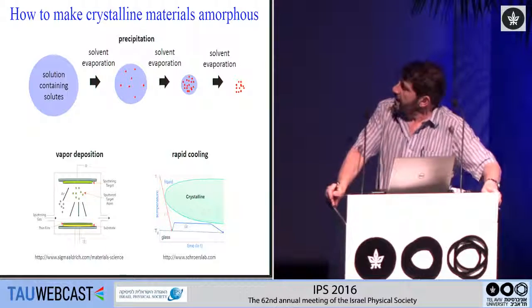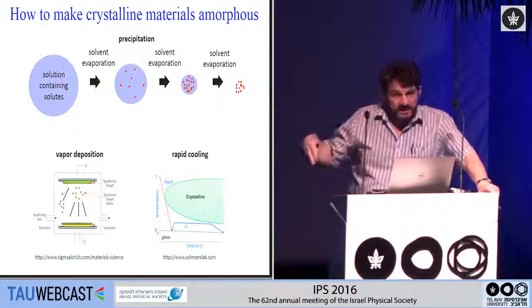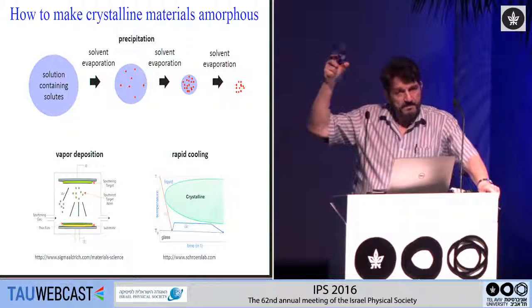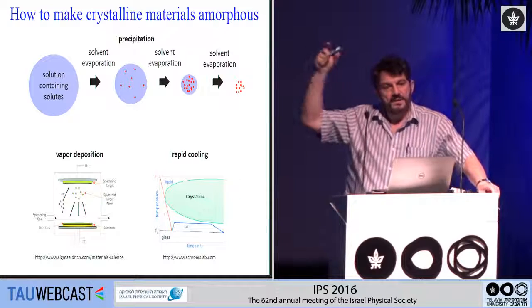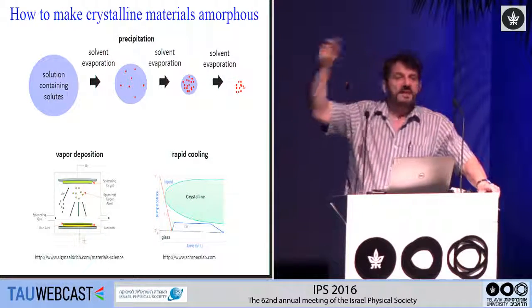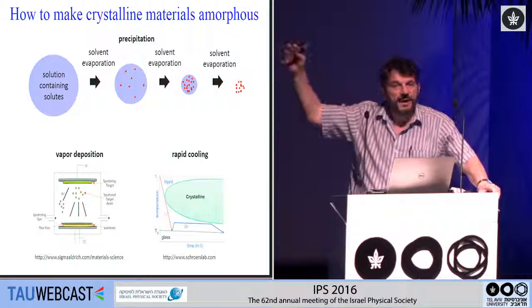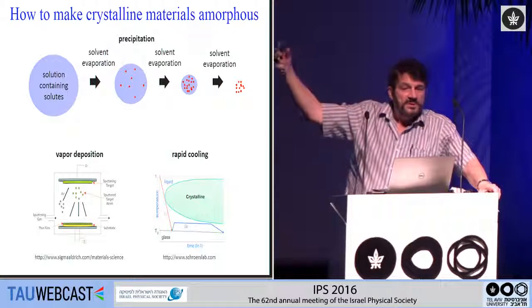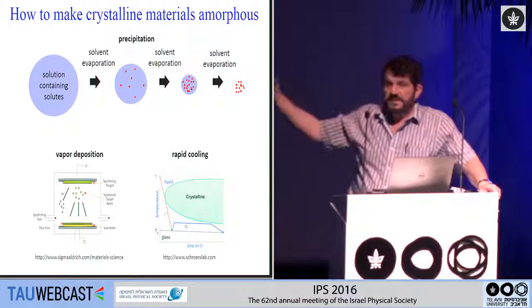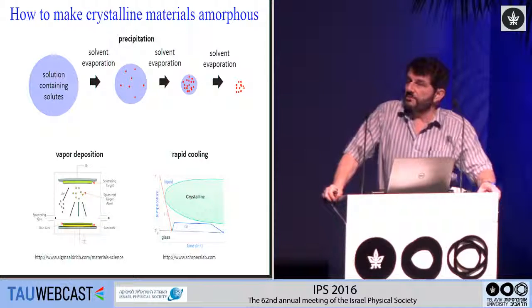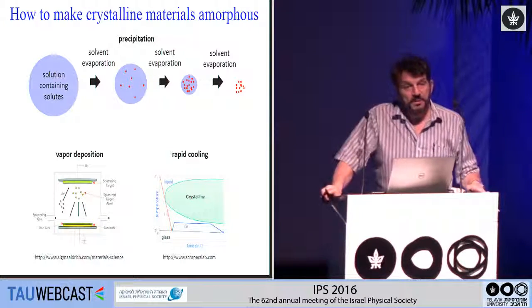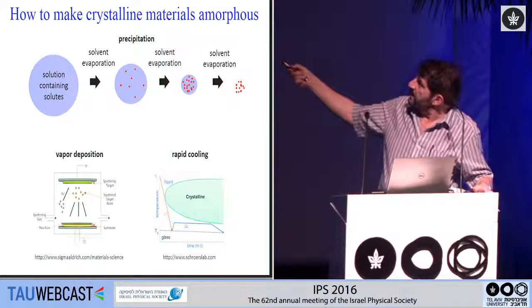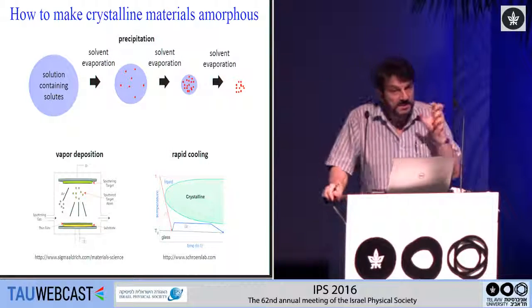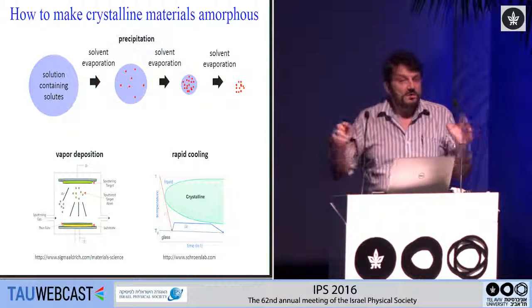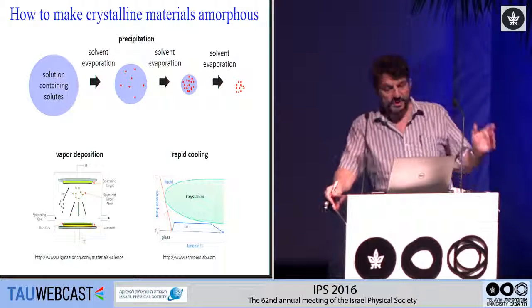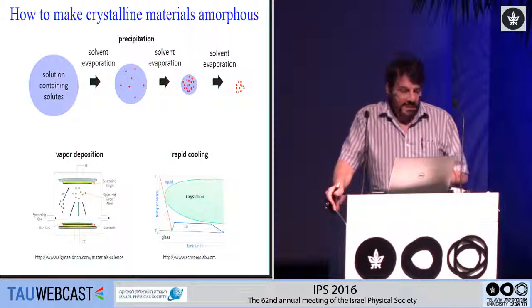A much more common way is to spray dry materials. Spray drying is nothing more than taking a material, making it soluble in some solvent, making a small drop of the solvent and blowing it through hot air to evaporate the solvent, and the precipitate becomes a solid particle. It's a very standard, very widely used technology for making materials, and you would think that it would be a very good way of making an amorphous material, basically because as you evaporate things, you might be able to make the material become amorphous. However, unfortunately, crystallization is always faster than evaporation, or almost always faster than evaporation. So this always makes crystalline materials.